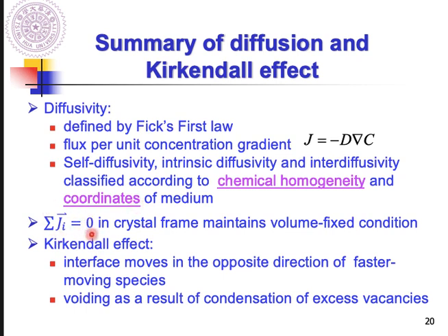And that's a very important principle. Actually, the total net flux should equal 0 in the crystal frame, and that will maintain the volume-fixed condition. Also, in order to determine whether the Kirkendall effect happens, you know there are two characteristics to demonstrate it.